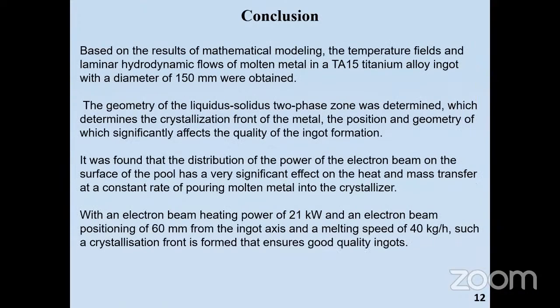Next slide. The slide presents the main conclusions of the work carried out. Based on the results of mathematical modeling, the temperature field and the laminar hydrodynamic flow of the molten metal in a TA15 titanium alloy ingot with a diameter of 150 millimeters were obtained. The geometry of the liquidus-solidus two-phase zone was determined, which determines the crystallization front of the metal, the position and geometry of which significantly affect the quality of the ingot formation.